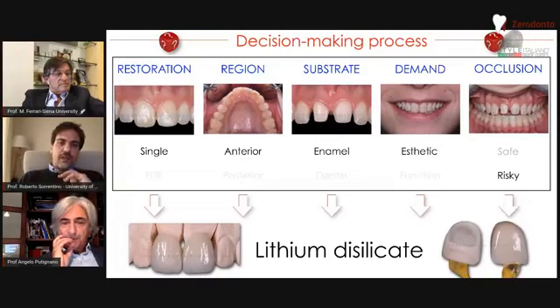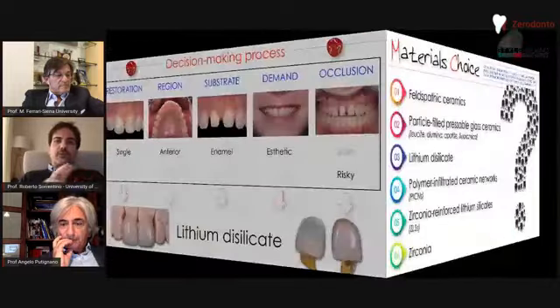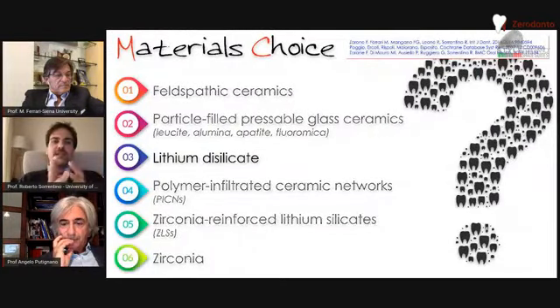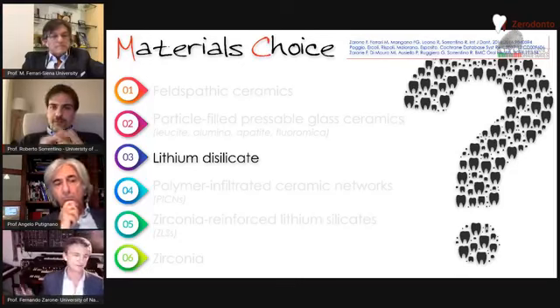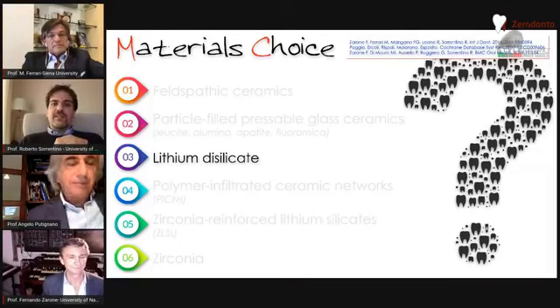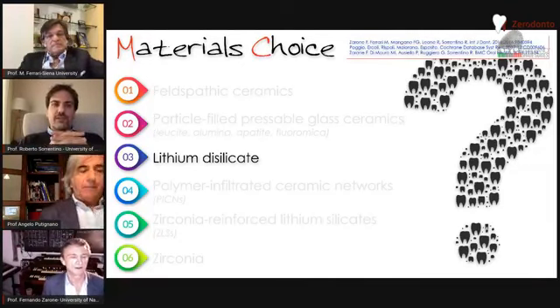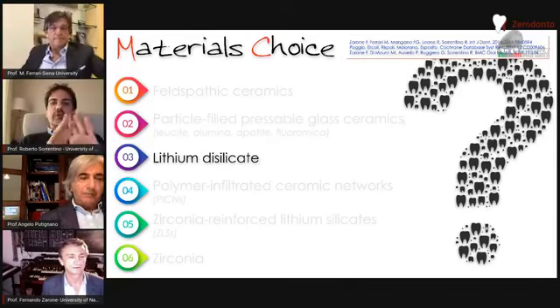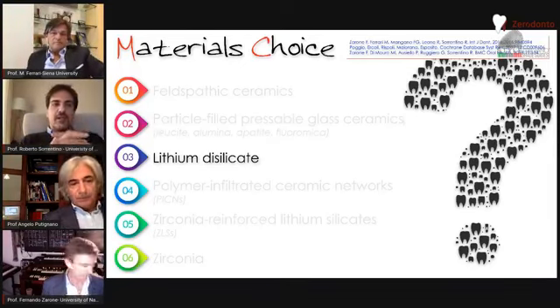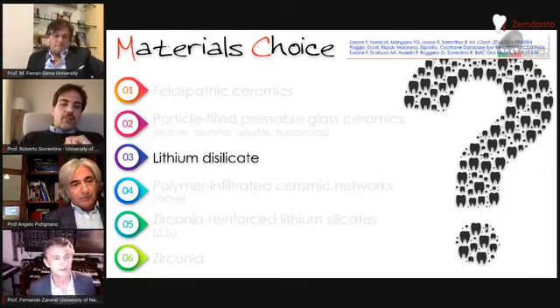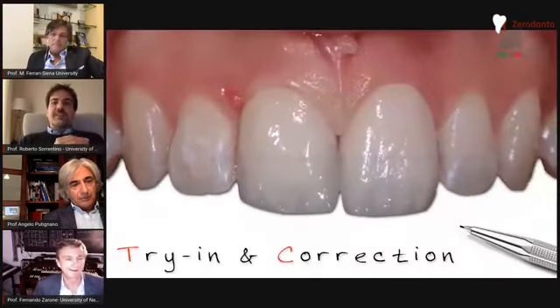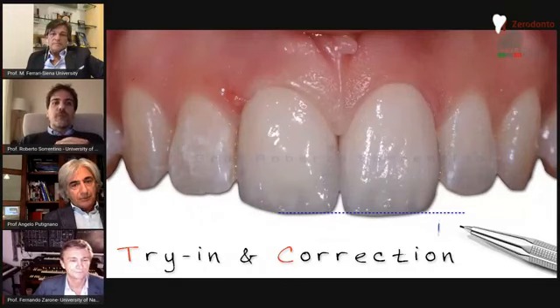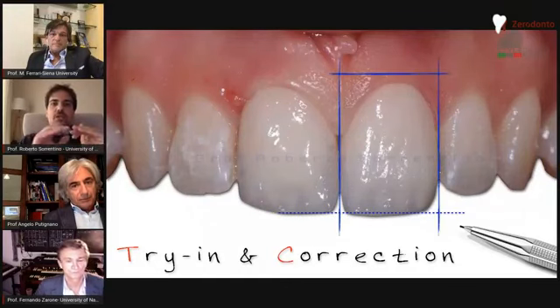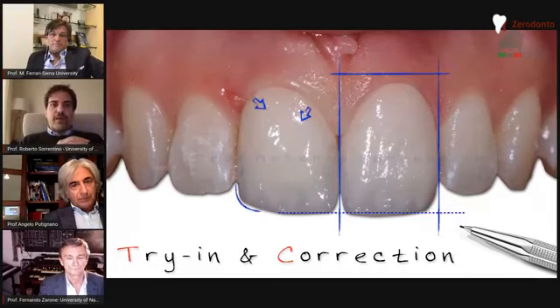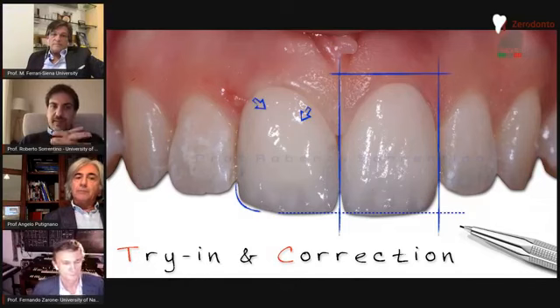And of course, it would be possible to use different dental ceramics for crowns and veneers, but I completely agree with Professor Putignano, and in my personal experience, and also according to the most recent literature, it is always preferable to uniform the materials of the restorations functioning together. And moreover, lithium disilicate prosthesis can be removed from the master cast to perform an intraoral try-in, a color check, and any possible correction before final finishing and polishing.